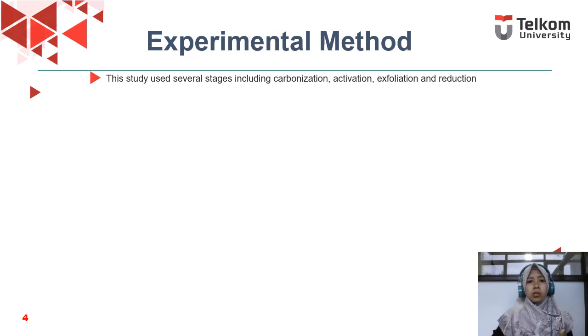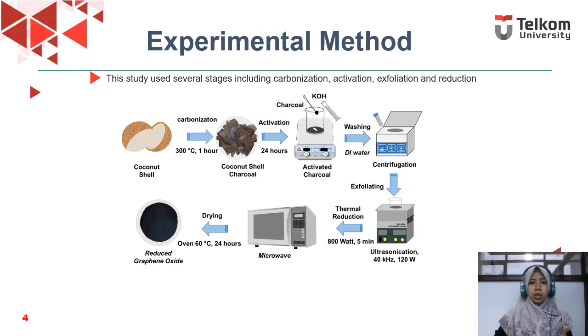The study used several stages including carbonization, activation, exfoliation, and reduction. For the first stage, the coconut shell was dried for 1 hour at a temperature of 300 degrees Celsius and then activated for 24 hours using potassium hydroxide as an activation agent. The sample was then washed using water and exfoliated using an ultrasonic bath. The last stage is the reduction process to remove oxygen functional groups using a microwave for 5 minutes.